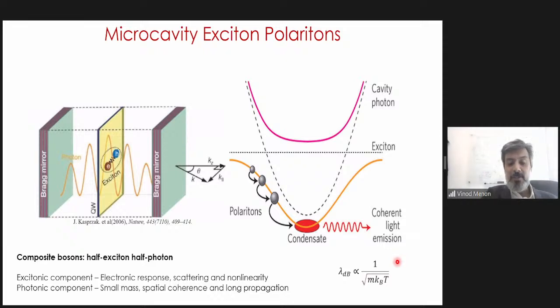First demonstrations were in 2007, 2008 by multiple groups. And essentially what happens there is you create the polaritons, they scatter, and you get a macroscopic coherent state, which shows all the condensation behavior. Now, sometimes people call them BECs or polariton BECs. One has to be a little careful about that because they're not true BECs, at least in most of the experiments done to date, because these are out of equilibrium systems. You have to constantly drive them. The photons are leaking out. So the polariton number is not conserved in this case.